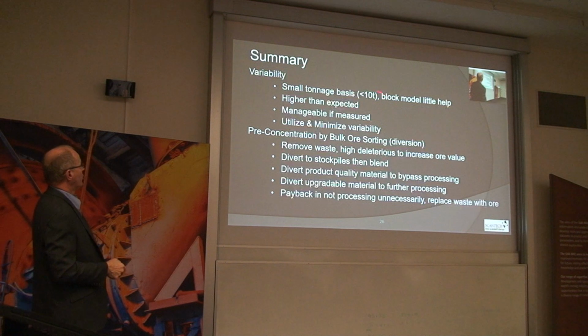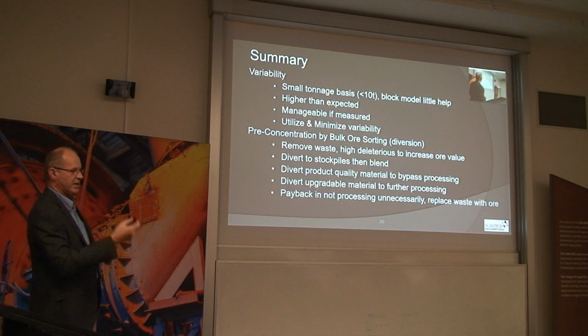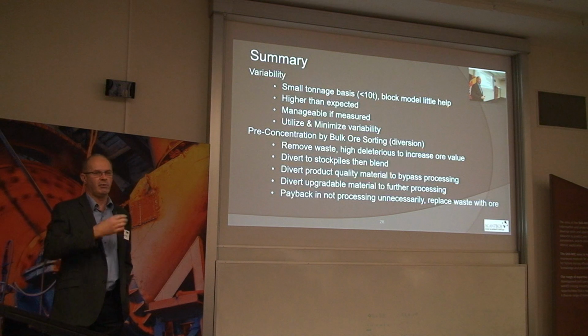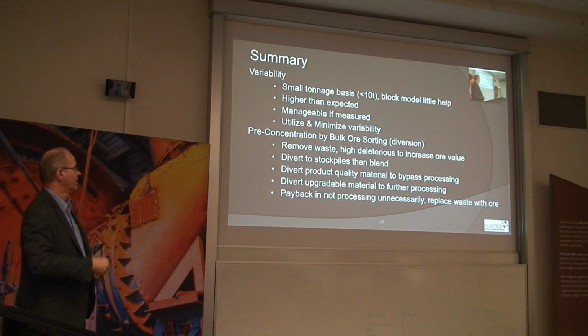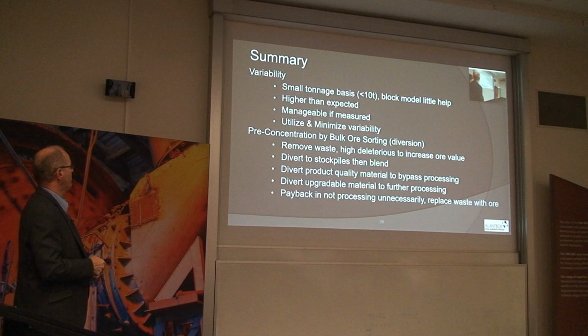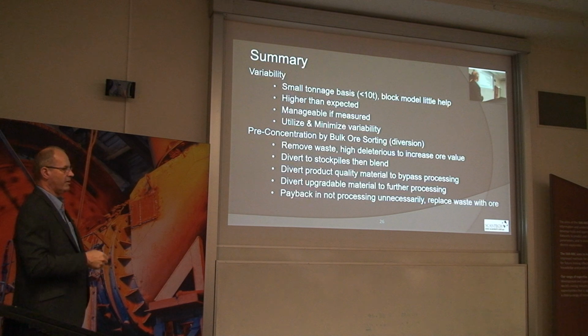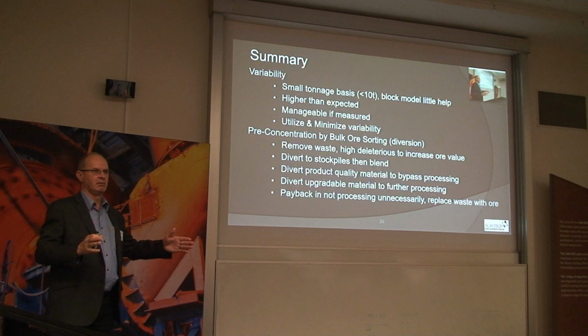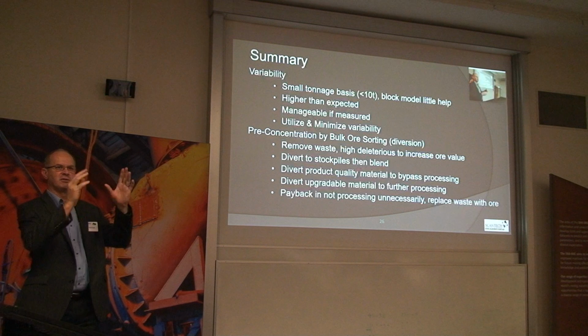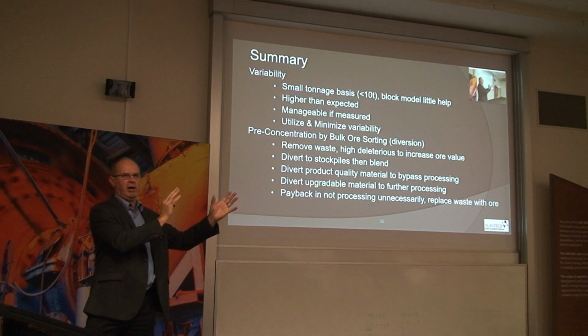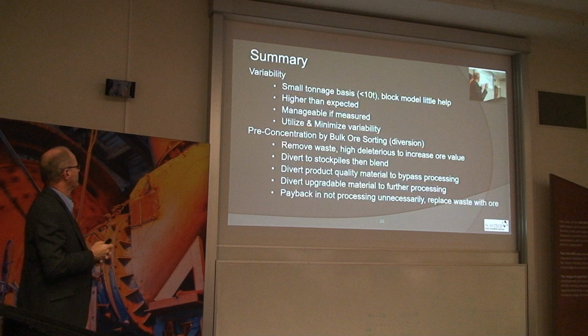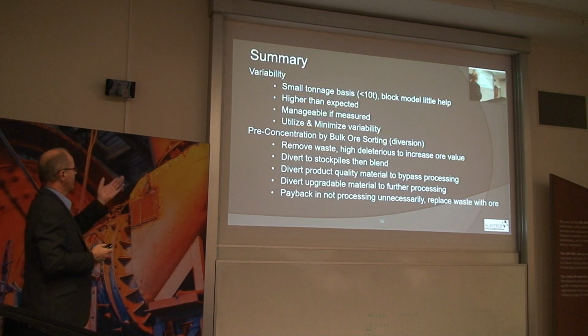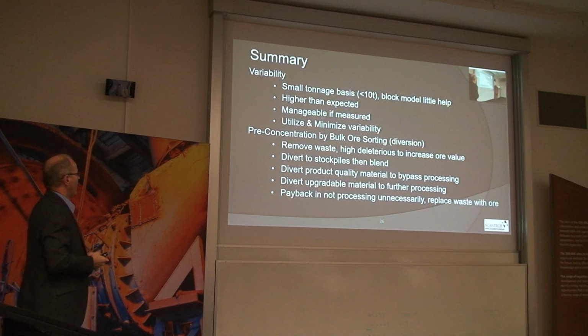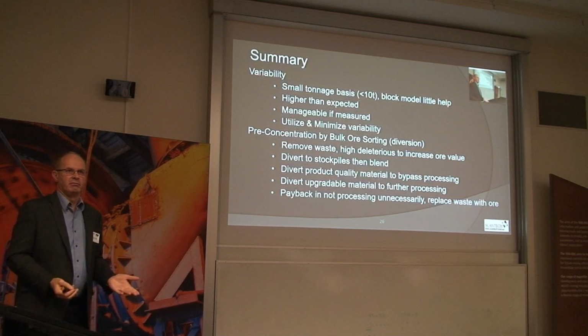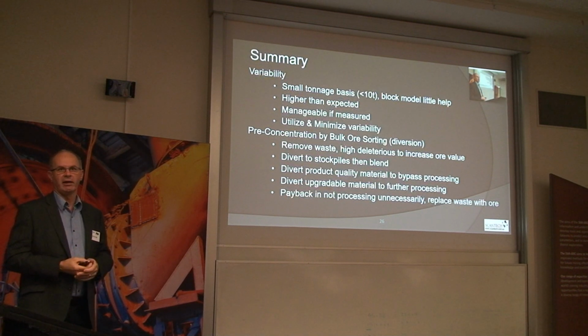Key thing here is we're looking at small increments. 10 tonnes is about the size of a loader bucket, and we're making decisions on every loader bucket equivalent with an accurate measurement. Variability is always higher than expected at operations on that measurement basis, because in their minds, variability is the difference between that block grade and this block grade, and they've all been averaged, so it's not as high as it actually is on a conveyor. And variability is manageable if you measure it. If you're not measuring it, there's nothing you can do about it except respond to it.